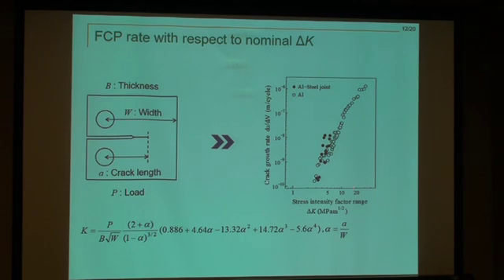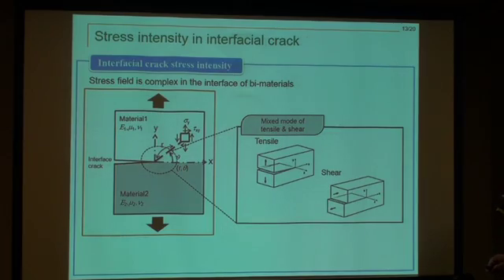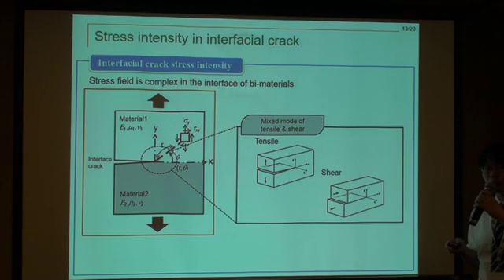This is just the graph which shows the crack propagation rate with respect to the nominal stress intensity factor range. However, as I explained, the stress field becomes complex in the interfacial crack, and the stress singularities of not only mode 1 but also the shear mode 2 appear. So this approximation cannot be used.